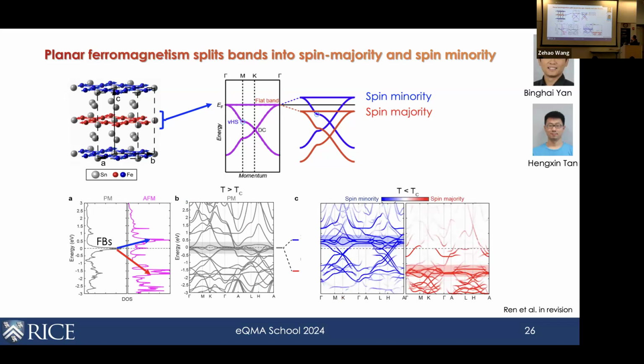And you can see this picture roughly in the DFT calculations. Here on the left-hand side is the calculated density of states. You see this large peak at the Fermi level. That corresponds to these topological flat bands associated with the iron Kagome layers, here in the band structure for the non-magnetic state. And then when they calculate the electronic structure for the A-type AFM order, they can see this flat band peak becomes split into two. When they project into the spin majority and spin minority states, they can see that those peaks correspond to the Kagome flat bands, which in this case are shifted down, and this is shifted up across the ordering temperature. So in essence, this picture is at least largely captured by DFT.